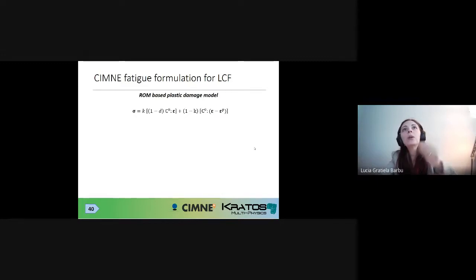Then we go to the rule of mixture-based plastic damage model. I have to say this is a model that I'm deeply in love with, because the rule of mixture is something that has been used in the composite world since the 1960s. It's a very old idea, but it has never been used for describing the behavior of a homogeneous material. What we are doing here is assuming that in a specific volume of a homogeneous material, we have a volumetric part which will behave according to plasticity laws, and the remaining, complementary volume part, which will behave according to damage.